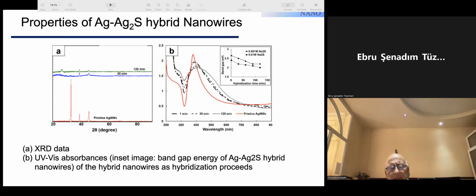The change of this band gap will depend on the concentration of the solution, the volume which we used for modification of the wire, and the quantity of sulfur ions in the used volume. Because it is interesting to investigate the dependence of this process on the concentration of the used solution.